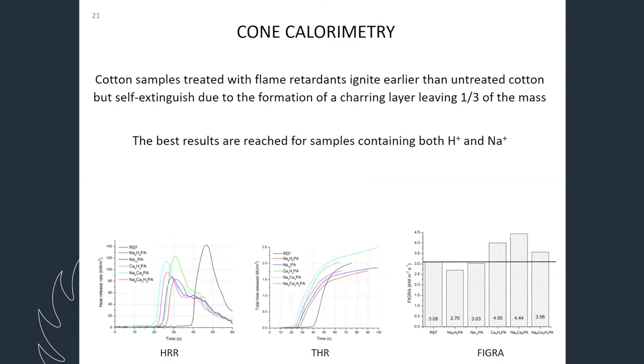We also analyzed our sample with cone calorimetry. We saw that when we take just untreated sample, that was burnt and disappeared completely in the cone calorimeter. But all the treated samples, as we saw in the burning test, they were retained after the cone calorimetry experiment.